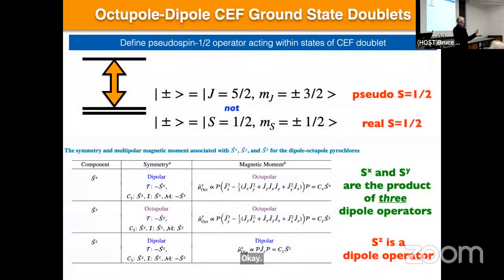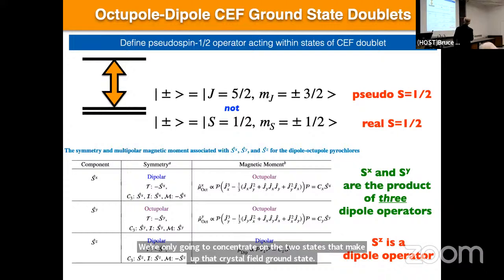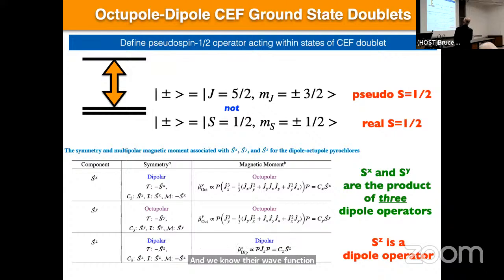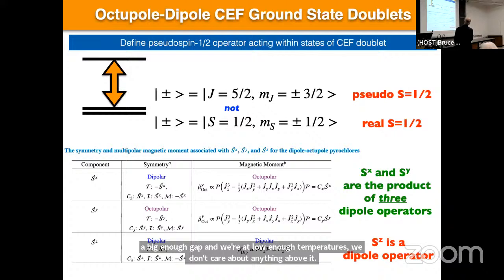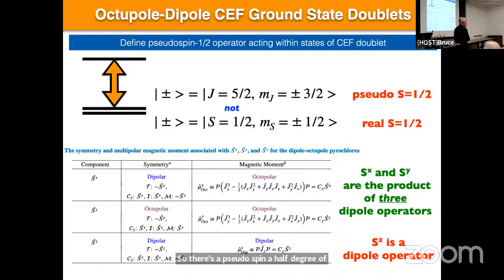Right. So we're going to forget about all the excited states. We're only going to concentrate on the two states that make up that crystal field ground state. And we know their wave function. Okay. And this is their wave function. So we've got this big gap. So once we've got a big enough gap and we're at low enough temperatures, we don't care about anything above it. We only care about these two states. So there's a pseudo spin a half degree of freedom because there's two of them. So this is similar to, but different from, a real spin a half degree of freedom.